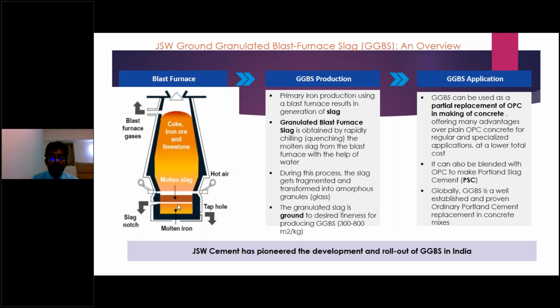The blast furnace slag is ground into fine powder, ranging from 300 to 800 square meters per kg. The GGBS we are making is 3,800 square centimeters per gram, or 380 square meters per kg. But if you grind the same GGBS more finely, we can make ultra fine GGBS that is used for high grades of concrete. For general normal grades of concrete up to M60, we use this material called GGBS.